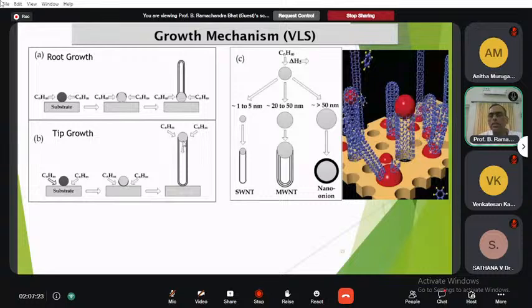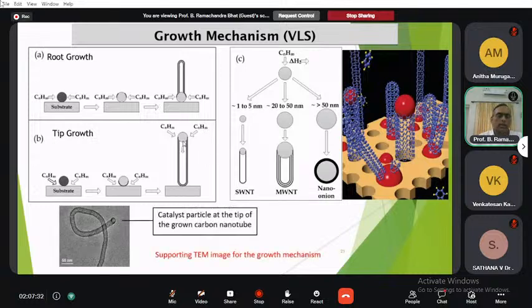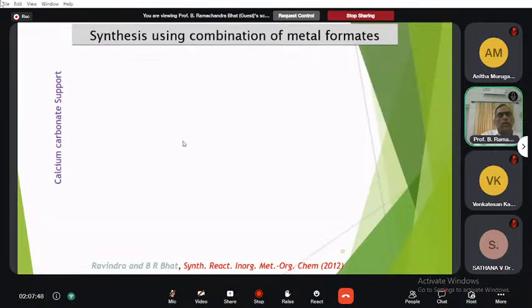So this is the model which shows the tip growth as well as the root growth methods. You can see here in this material what we prepared, a catalyst particle at the tip of the grown nanotube. That's a carbon nanotube. This TEM image supports this growth mechanism. Now, synthesizing the carbon nanotube using a different catalyst.